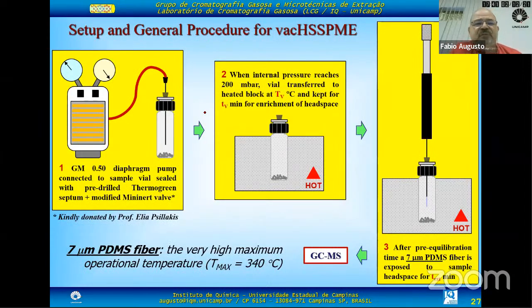Well, the procedure was very simple here. We enclosed the solid sample in a vial with pre-drilled thermogreen septa in modified Mininert valves. Mininert valves are valves for headspace sampling. Professor Elia Psillakis donated them for us, but it's very simple to prepare. We evacuate it with a low-cost pump. It's a GM 0.5 pump, a pump that costs less than $500. It's a very simple Chinese-made pump.